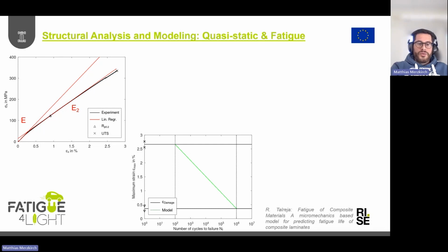Now the aim is to go to a strain-based S-N curve as shown here. How are those numbers determined? We are using strain-related damage onset. Damage onset in the lower region, at the knee, where the specimen got darker, and of course full damage, which is the ultimate tensile strain here. We use those two limits, and in between is a model. So that's a rough estimate that from 100 cycles to 1,000,000 cycles there is this kind of behavior. If an airplane were designed like that, I would not enter it. So in that case, we need a verification.